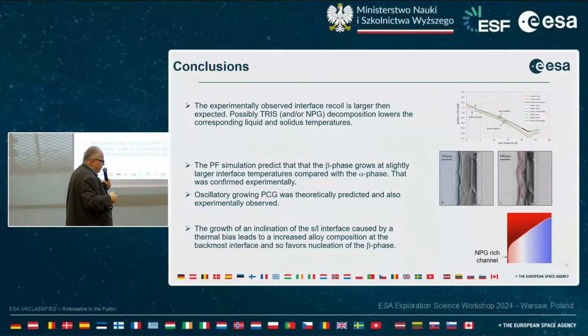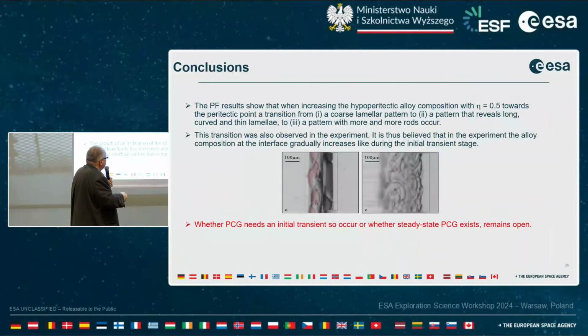And we found what was predicted by the phase field simulation. As we found the patches, we found that one phase overgrows the other one, and we found out that it's coming from this NPG enriched channel, so there was no nucleation observed on the solid liquid interface. Okay, and this was the last one that we have in this transition from patches to rods, but we found this in one sample over the time, 90 hours, means more or less 1 day work.